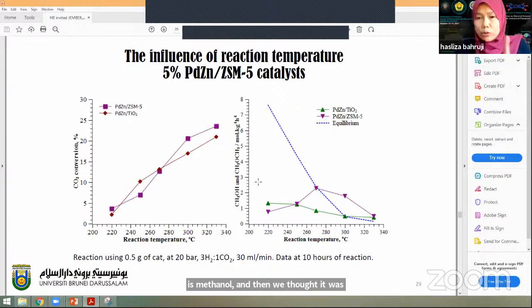We no longer produce a high concentration of carbon monoxide. This is very important. It tells us that yes, we managed to intercept methanol and convert the methanol further to dimethyl ether instead of the reverse water gas shift reaction. And we can see that at 270 up to 300, we actually defy the thermodynamics, because a quick interception of methanol gives the edge to the equilibrium process, pushing the equilibrium towards the production of dimethyl ether and methanol.